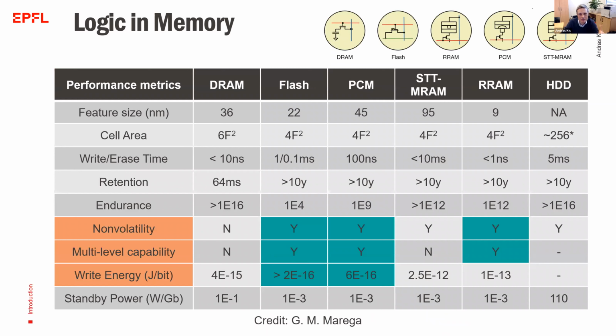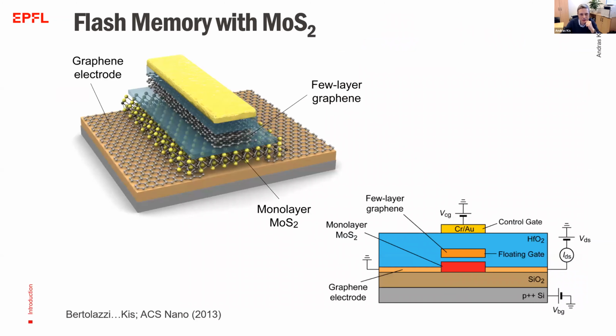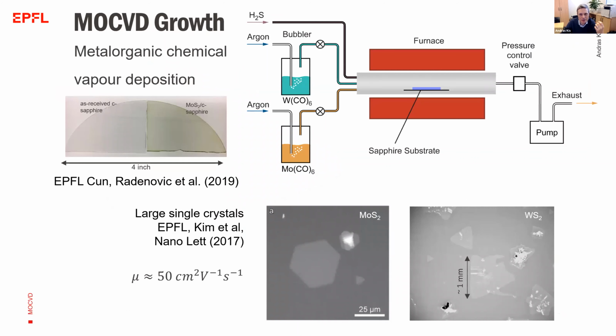And when we did some review of this data and numbers, we realized that one which is relatively useful and is also very close to us are the flash memories and flash memory elements. So back in the early days of 2D devices, we realized the first flash memory elements based on MoS2, and it was shown that in principle you could make both transistors and memory elements using the same materials. So thinking more about this, we decided to refresh a little bit the design and try to make these devices in a more scalable way.